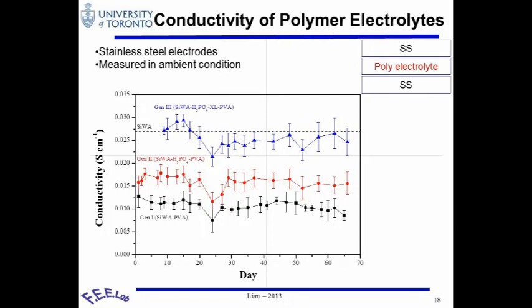Look at the three types of generation. The first one, as I said, is 2 components, so it has about 0.01 Siemens per centimeter in terms of conductivity. And the Gen 2, now we're adding a small amount of phosphoric acid, the conductivity did increase. And the third generation, we add more cross-linking agent, and the conductivity actually gets reached about 0.025.